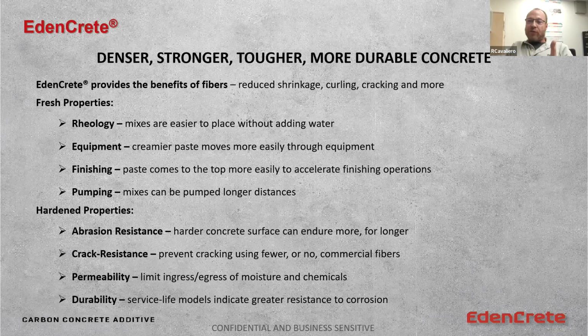When you look at concrete's internal structure, you see a lot of holes. When you look at the surface, you often don't see as many. So keeping that surface on helps to prevent the ingress and egress of moisture. The carbon nanotubes physically arrest those cracks, right? So they don't stop cracks, but when cracks occur, they will occur and be of a smaller size. And ultimately, the rate of propagation will be slower. And then the magnitude that they ultimately grow to will be smaller.